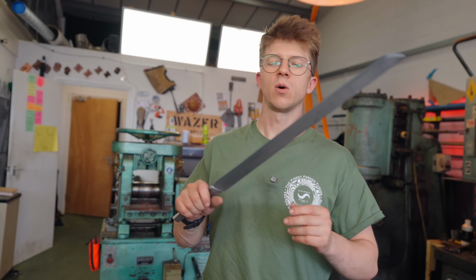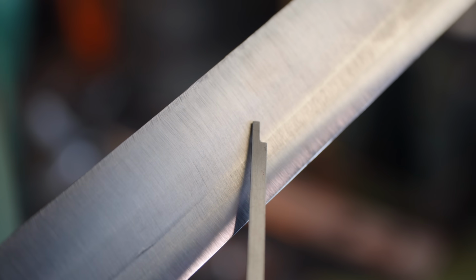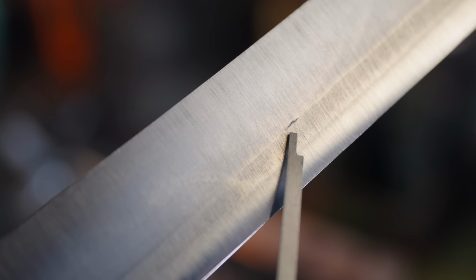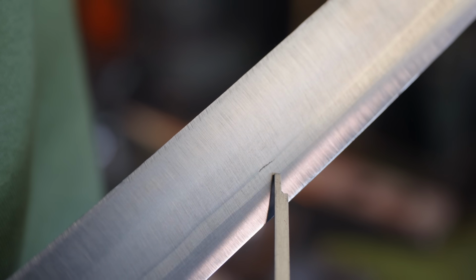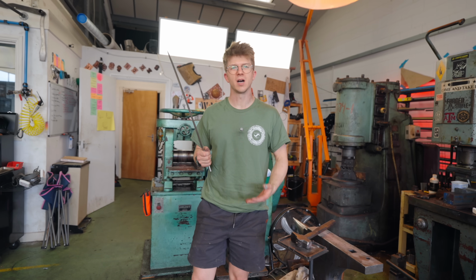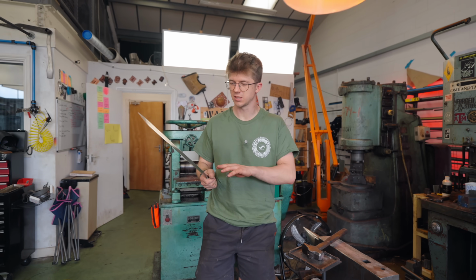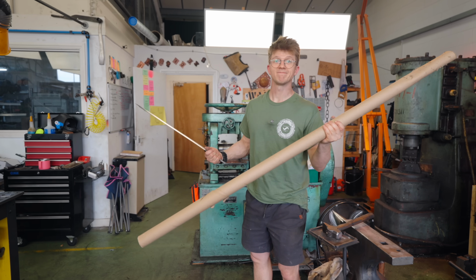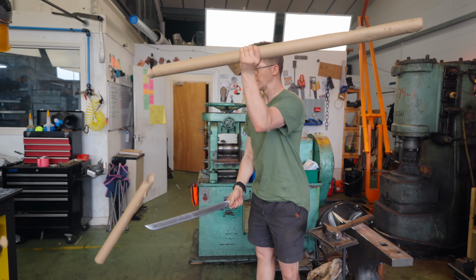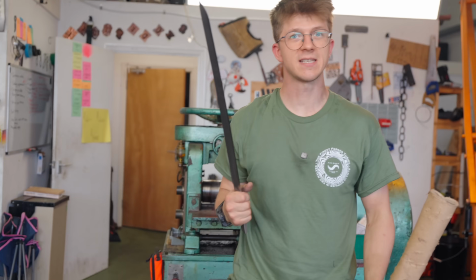Now, what have we noticed while we were grinding it? Here's our steel, here's our nickel interlayer, and there is our titanium. But have a look at this. Got a few little voids between the nickel and titanium there, here, and there on the other side, which would obviously be unacceptable for a final piece. This is just a test. It's only rough ground. We're going to find out if it'll break. Let's stress test it.